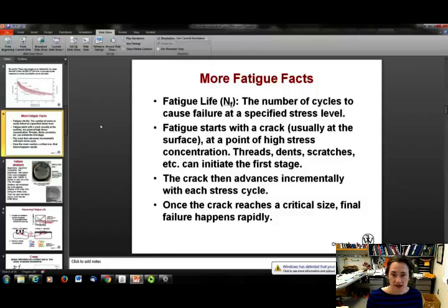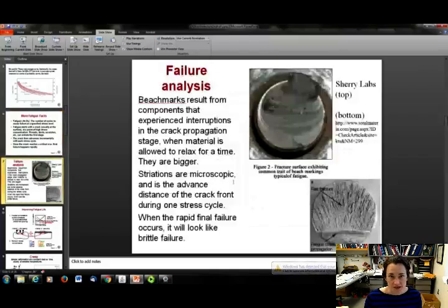And then in the second stage, that crack that's formed will advance incrementally with each stress cycle. So every stress cycle, the crack will move a little further, and a little further, and a little further. When it's reached some critical size, then the final failure will happen like that. And that's why we say that fatigue failure happens without warning, because if you don't know the crack is there, all of a sudden the part will just fail one day and you've got yourself what looks like a brittle fracture failure.